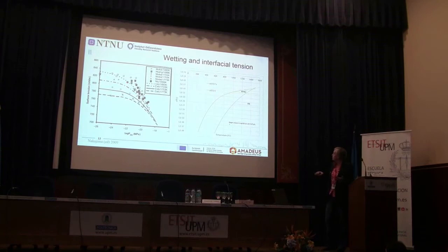If we are looking at two different systems, like the way we are doing experiments in Trondheim, we are using a lot of carbon in our furnaces, so our oxygen pressure will be determined by the carbon material. Then the oxygen pressure will be like this as a function of temperature.